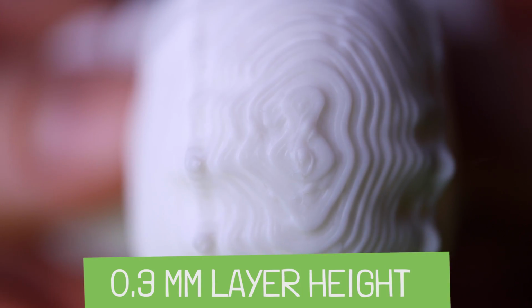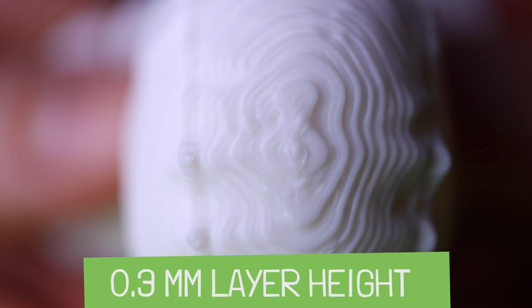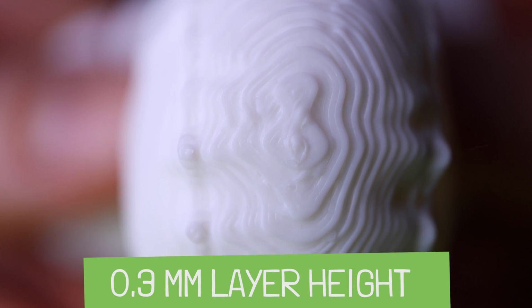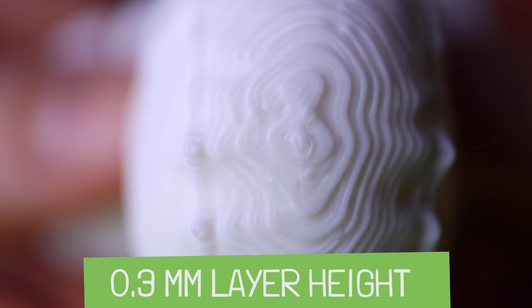And then lastly, just a little bit step above that is a 0.3 millimeter layer height. Now, this is where you can get some issues, and I will show you right there. My extruder could not push out enough to get good layer adhesion. So it was actually starting to pull apart. I could honestly probably pull this apart right now. And if you're looking in some of the details, they're just not there. And it is not a great print.